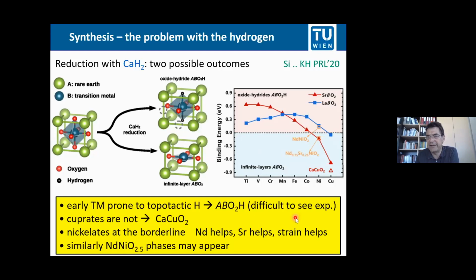So if you do X-ray, the hydrogen is a small atom. You don't see the hydrogen in a standard X-ray procedure, which our experimental colleagues typically do. You do see if you have some excess oxygen, like having one oxygen atom instead of two hydrogen atoms here, that occurs very often. But these phases can be more easily thrown away if they occur in your synthesis procedure.